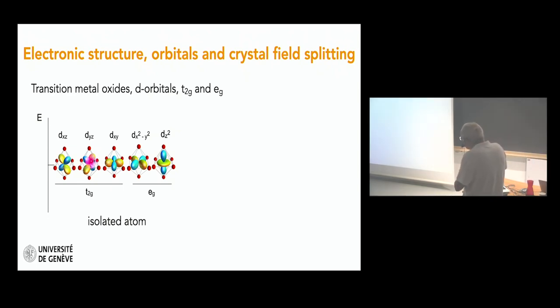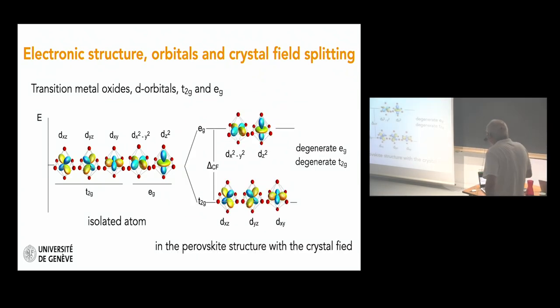And now, this is easy to understand, if you look at the t2g orbitals, you realize that the orbitals are pointing away from the negatively charged oxygen atoms. But the eg orbitals are pointing towards the oxygen atoms. And so there is a repulsion, this is costing energy, and this is lifting the degeneracy. And this is now the crystal field splitting. So in our perovskite, we have our t2g orbitals, which are here, separated from the eg orbitals by this crystal field splitting, which is large, a few electron volts.